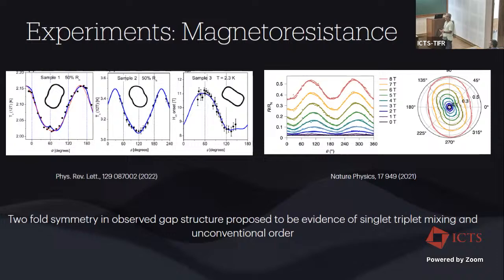Now, if you look at essentially the irreducible representations of your system or all possible superconducting gaps, it is very hard to reconcile for a conventional mechanism the formation of a twofold gap out here. First of all, you need a multidimensional representation, but within that multidimensional representation, you need a scenario where it chooses essentially one of the 1D states. It does not choose one of the 1D states to get this possibility out here. In this particular paper, they said that probably it is a multidimensional representation playing a role, but even for that, it won't work for a weak coupling ground state. So the question remains, what would be the solution?